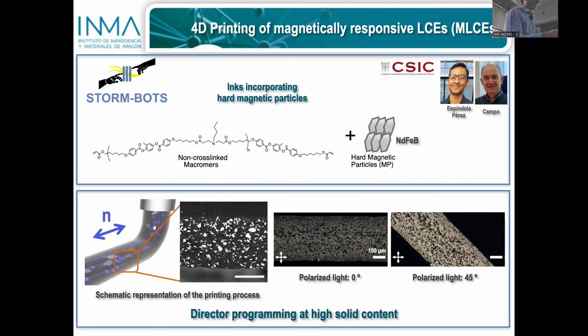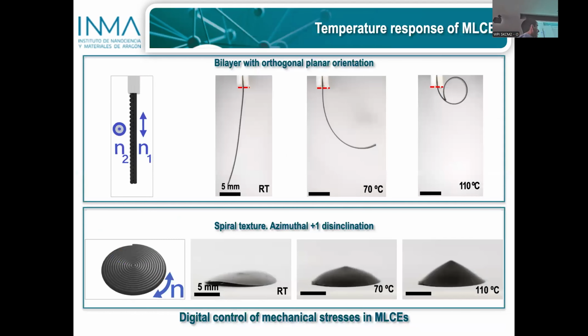So we can program the director even having such an amount of particles. That is an advantage that is not possible with conventional techniques. Here you have a bilayer, like a twisted nematic, and on heating, of course, we get this bending, and again the azimuthal sample that turns into a cone on heating.